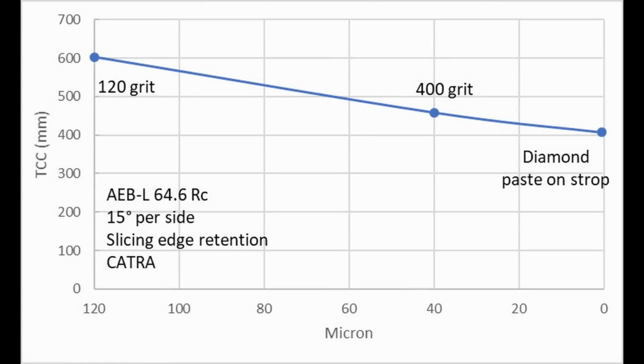The factory sharpened knife edges instead have a more convex shape, which makes them behave more like an edge sharpened to a more obtuse angle. The factory knives were given a polishing step at the end of sharpening, which is what was rounding those edges some. My knives were sharpened to 400 grit, which is relatively coarse, which gives the steel enhanced slicing edge retention. So again, the polishing step on those production knives is making the edge less aggressive, and it doesn't cut as long in a slicing test like with Catra.